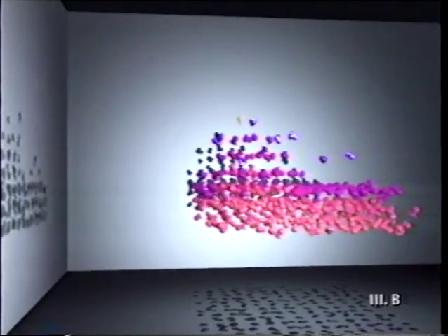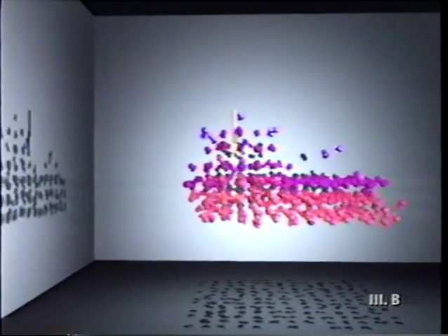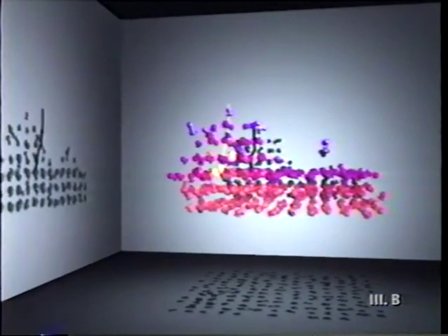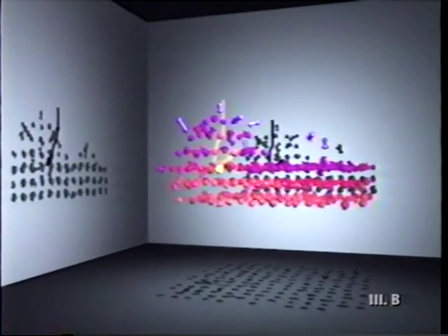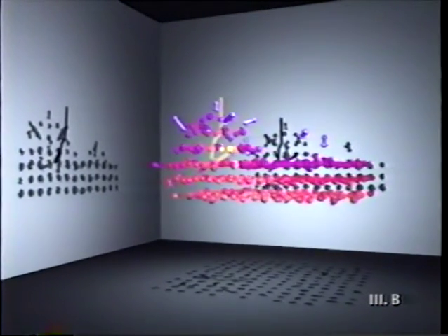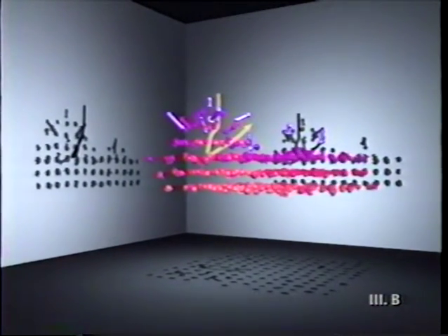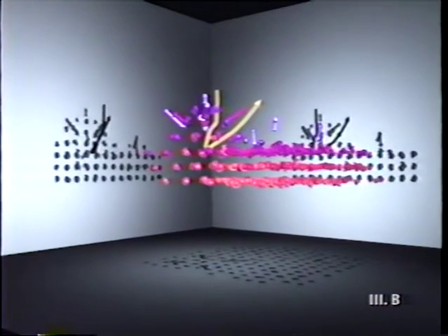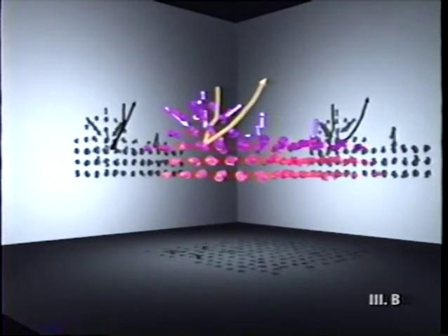The interactions of the hydrogen with the nickel atoms are primarily elastic. The hydrogen atom emerges from the simulation with 8.5 eV of energy. However, due to the large mass difference, little net nickel displacements, or persistence of directed nickel velocities, remain. Even the velocities of the two hardest hit nickel atoms have returned to thermal energies in the 40 femtosecond timescale.